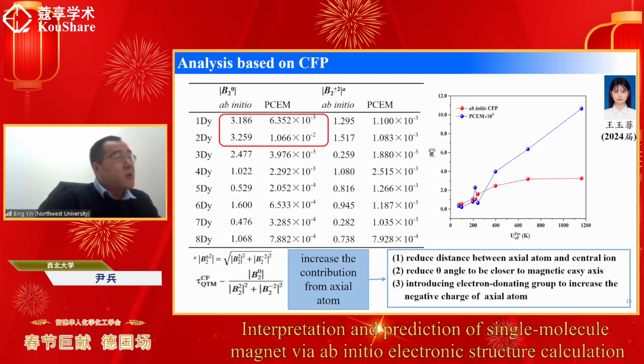And also, based on the PCEM model, we could find ways to increase the single-molecule magnet performance of the system. That is, increase the contribution from the axial atoms. We can reduce the distance between the axial atom and the central ion. We can reduce the angle between the axial atoms and the magnetic axis. We can also introduce an electron-donating group to increase the negative charge of the axial atom.